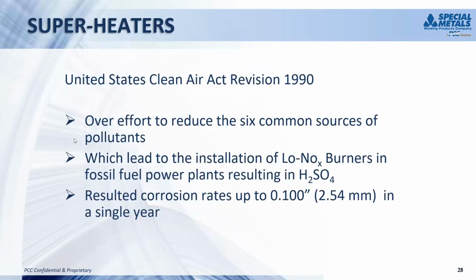Superheaters is another area of a lot of concern. In the United States, there was a Clean Air Act initiated in 1990. Parts of the world started a little earlier, some a little later, but the overall reason for this was to reduce pollution. Instead of letting a lot of these nasty components out into the atmosphere, we wanted to capture them and keep them maintained in the power plants. The downside is you're now keeping some very corrosive materials contained in the power generating system, which can concentrate and become very corrosive very quickly. Lew will talk a little more about that later, but once these low NOx burners were put in place to reduce emissions, you started seeing some very aggressive corrosion rates in a lot of these materials.